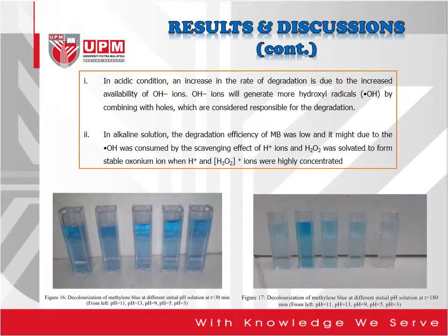This is because in acidic condition, an increase in the rate of degradation is due to the increased availability of hydroxyl ion. Hydroxyl ion will generate more hydroxyl radical by combining with holes, which will increase the rate of degradation. Moreover, it was analyzed that the improvement of the decolorization efficiency at acidic condition may originate from the dissolution of the copper compound, which is the catalyst, while in alkaline solution, the degradation efficiency of methylene blue was low,